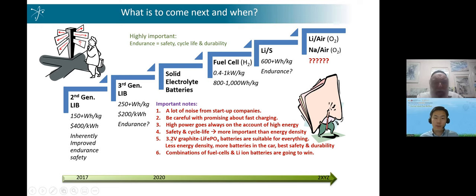It appears that 3.2 volt graphite LFP are suitable for everything. And in fact, simply by putting more batteries in the car, you can ensure very prolonged driving. And also, fortunately, LFP is also relatively fast. It's relatively fast because you can make it nano because of the relatively less reactivity of the oxygens of the phosphate with the electrolyte solution compared to transition metal oxide. So this is in fact a case, lithium iron phosphate, a case for a nano structure, maybe profitable, maybe useful.